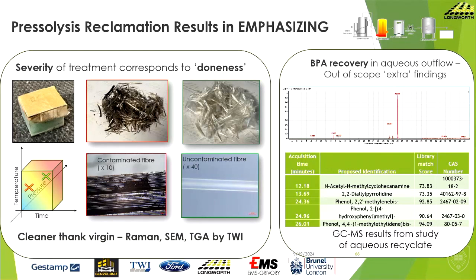And TWI verified that this was cleaner than virgin. Well, what does that mean? The sizing, the coating that allows the fiber to bond with the resin was removed. So we can start again. We can have a new application and we can size it for what we want. So in this case, we've gone from an epoxy to a virgin fiber to a thermoplastic nylon.